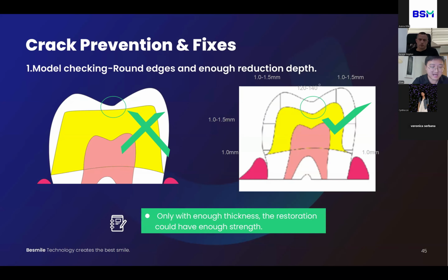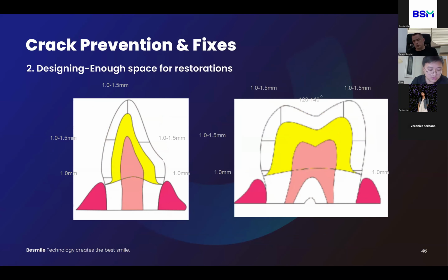And when we design, we also need to make sure there is enough thickness of the restorations. No matter what design software you use, 3Shape or EXOCAD or some other type of designing software, we have to make sure the thickness is at least 1 millimeter. This is a requirement for the full contour crown, full contour restoration. If you are making a coping bridge, we need to make sure the thickness is at least 0.5 millimeters.